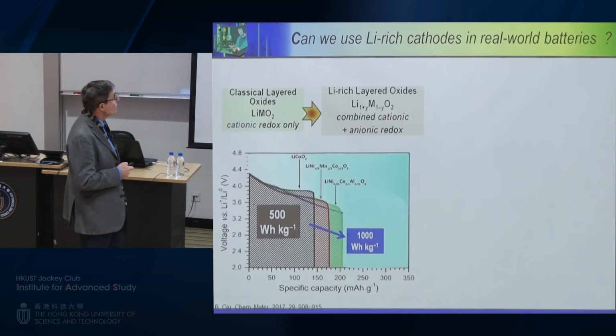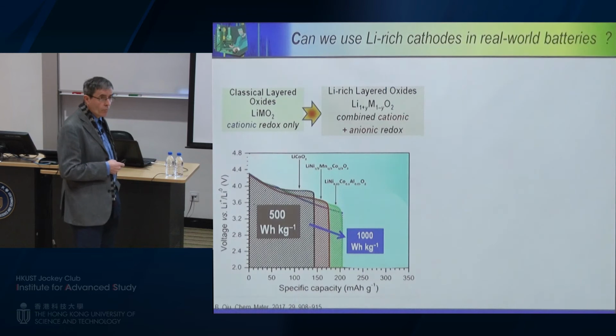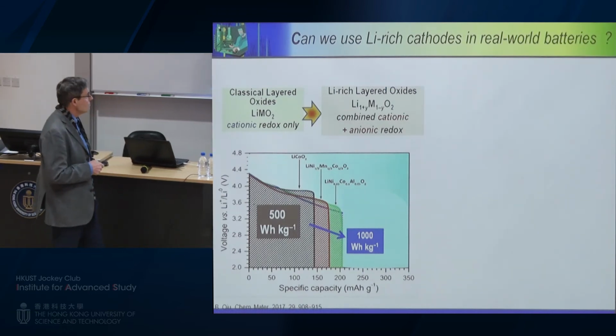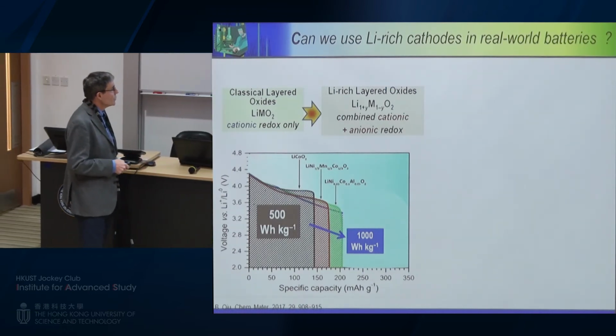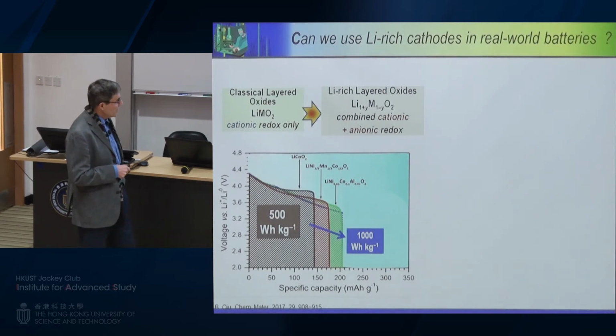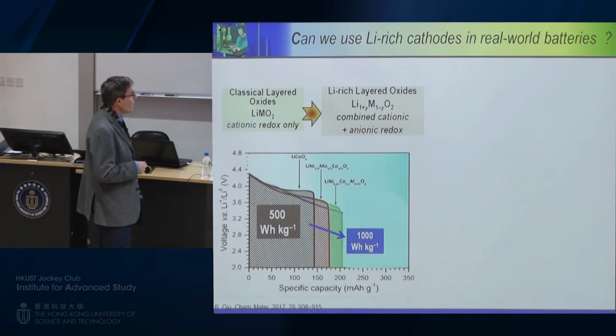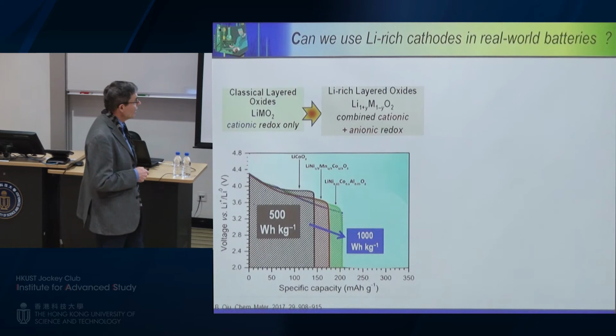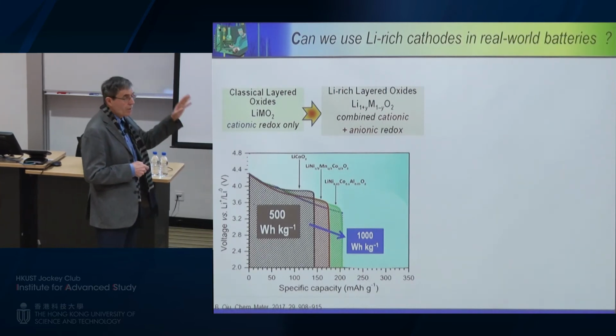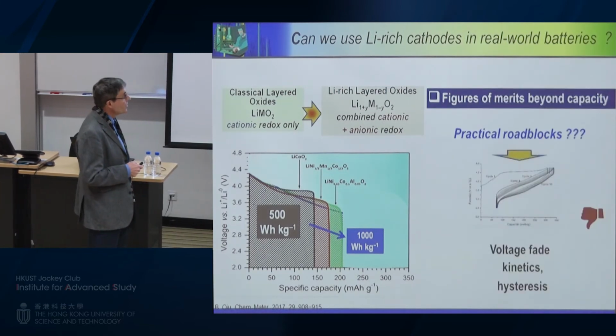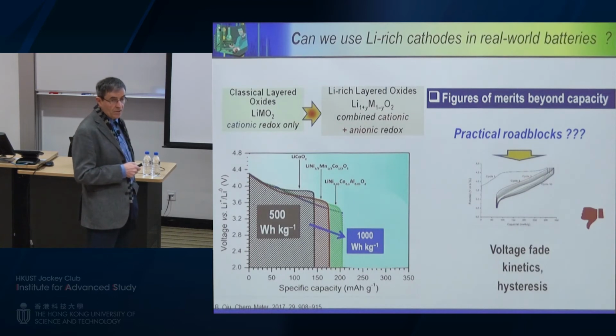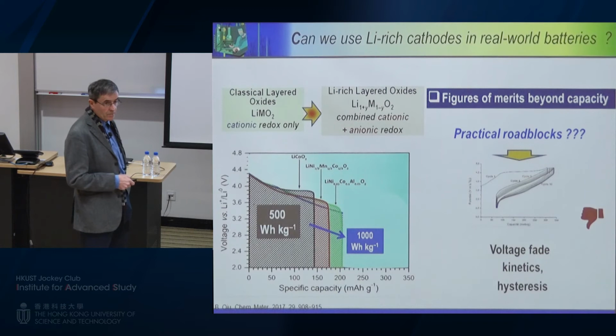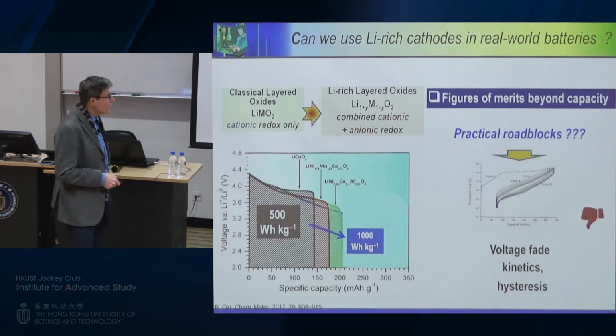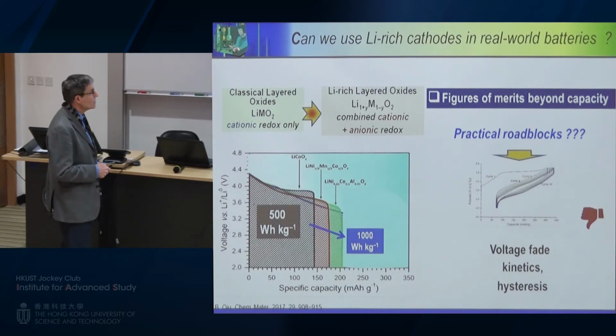Indeed, we built a large amount of hope into these materials based on the fact that we have a specific energy of 1,000 watt-hours per kilogram. But this is not the only figure of merit. And you are going to see that we have serious practical roadblocks. As I mentioned to you, first, the voltage fade. We also have issues of kinetics and issues of hysteresis.